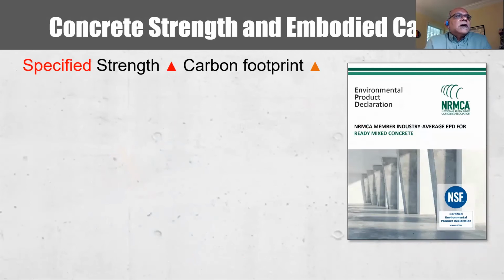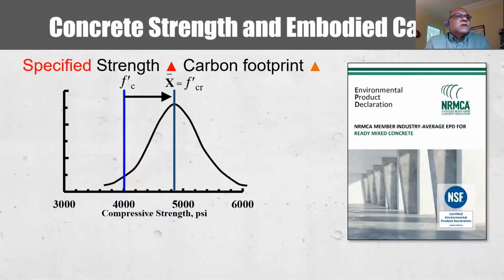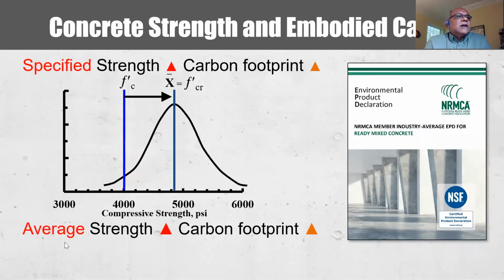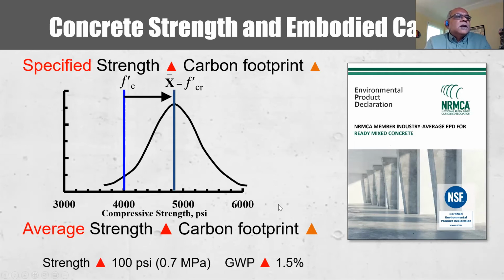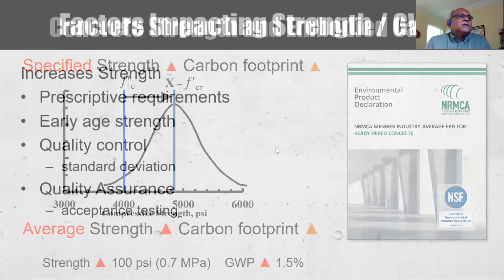Generally, as we talked about, as we increase the specified strength, we increase the carbon footprint of concrete. Again, as we increase the average strength by prescriptive requirements, we further increase the carbon footprint of concrete. And the carbon footprint, in an environmental benchmark such as the industry average that NRMCA publishes, is linked to the specified or design strength, but the reality is that what drives it is the actual average strength. And there are factors that force the average strength to be much higher than is intended for a specified strength. In general, a rule of thumb might be that an increase of the concrete strength by 100 psi increases the global warming potential by about 1.5%.